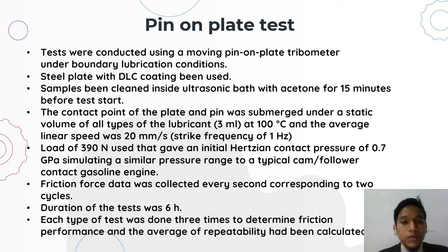Pin-on-plate test. Tests were conducted using a moving pin-on-plate tribometer under boundary lubrication conditions. A steel plate with DLC coating was used in this experiment. First, the samples were cleaned inside an ultrasonic bath with acetone for 15 minutes before the test started. Then, the contact point of the plate and pin was submerged under a static volume of the lubricant at 100 degrees Celsius and the average linear speed was 20 mm per second. A load of 390 Newton was used that gave an initial Hertzian contact pressure of 0.7 GPa, simulating a similar pressure range to a typical gasoline engine.